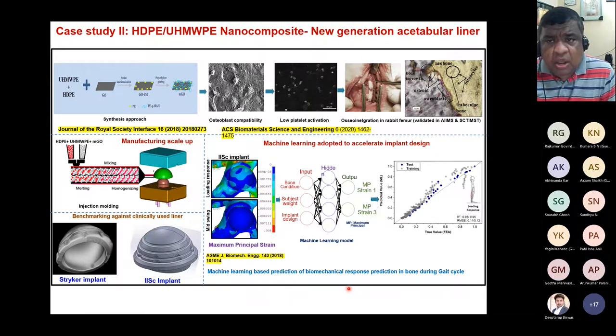Now, traditionally, most or all acetabular liners are essentially manufactured from an extruded rod, followed by machining to get different sized components. So what we have done, we have utilized a new concept called polymer blend, because UHMWPE cannot be injection molded because of the very high molecular weight and resultant high viscosity. So when we blended with high density polyethylene,